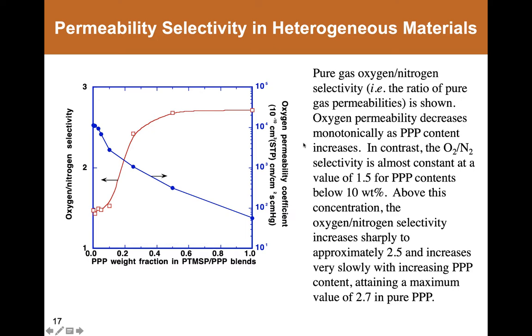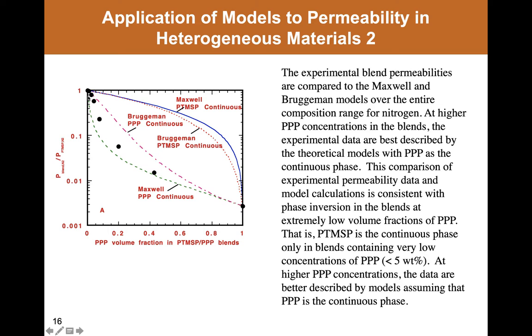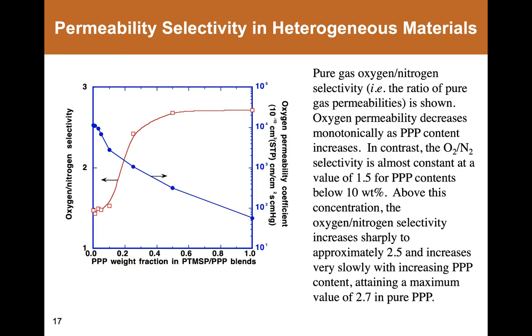And so a consequence of this is that you can imagine, for example, that in this case, PTMSP is more than two orders of magnitude, almost three orders of magnitude, more permeable to nitrogen than is polyphenylpropyne. As a result of this, it would be easy to imagine that the selectivity of polyphenylpropyne, since it's so much less permeable, and there is this permeability selectivity trade-off rule, that the selectivity of the polyphenylpropyne to a gas pair like oxygen over nitrogen would be higher for the polyphenylpropyne than it would be for PTMSP. And so one can see how the selectivity varies as the concentration of, for example, polyphenylpropyne in this blend varies across the composition range.